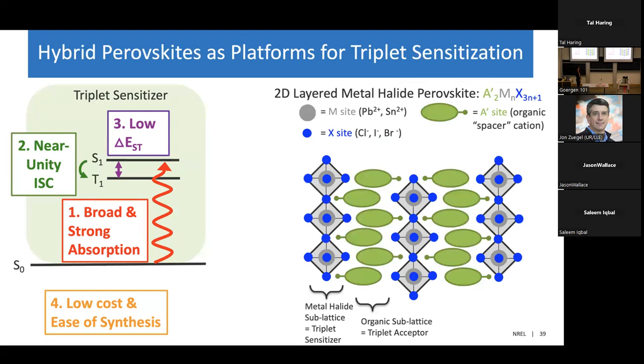All right. So what's really nice is these are excitonic materials. So again, they have very tunable properties. And the presence of the heavy atoms in the metal and the halogen sites can induce spin mixing of your exciton within that layer. And then with an appropriately chosen organic chromophore, we can now try and drive a triplet energy transfer across the interface.